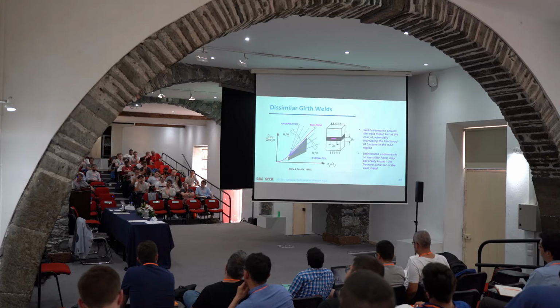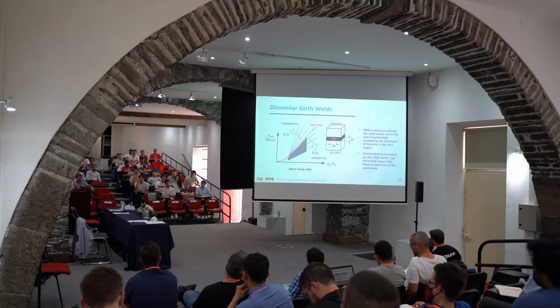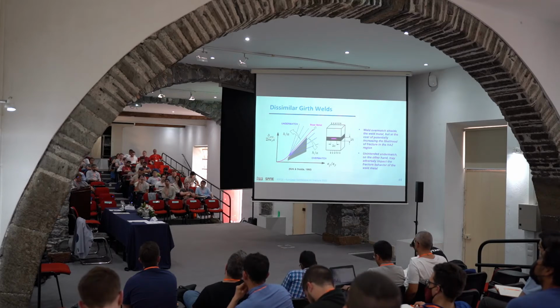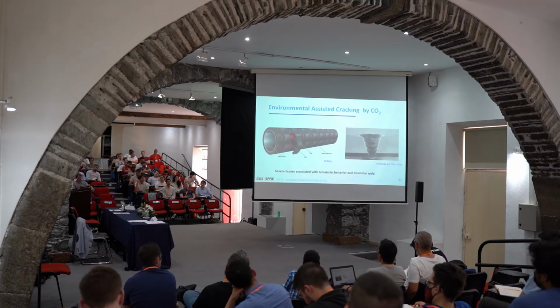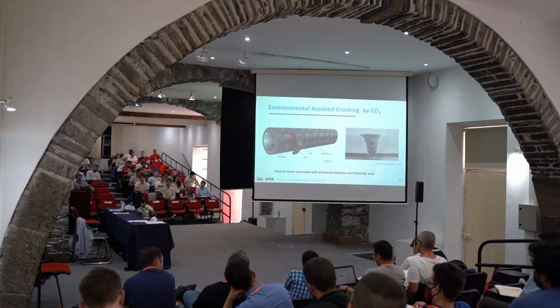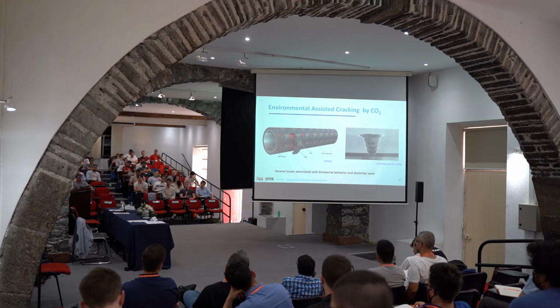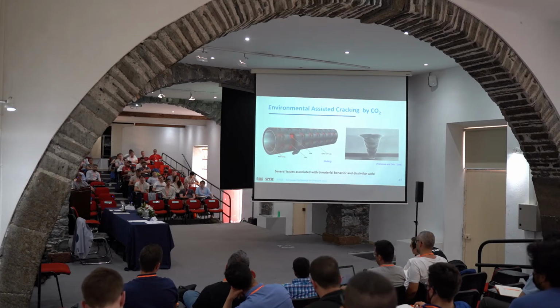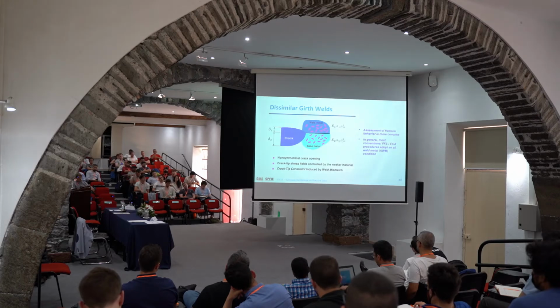This is overmatch, okay? But with this new generation of materials, for example, in the pipeline area, since the strength is increasing, okay, the hardening behavior is also decreasing, and the inconel does not have such a high strength. So usually when we have the similar weld made of inconel and X80, X70, in many cases you are going to have undermatch, or at least what is called partial undermatch. So it's undermatch at the beginning, and then because of the difference in stress strain behavior, the curve starts to deviate apart. Okay, that's a problem. That makes the behavior more complex.